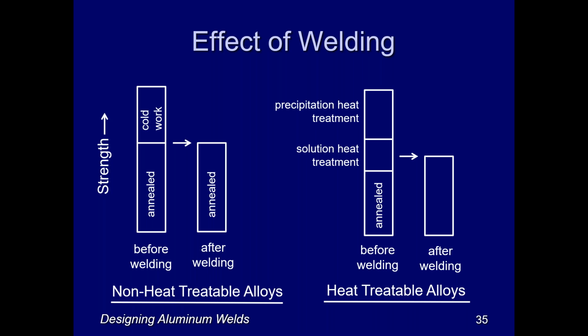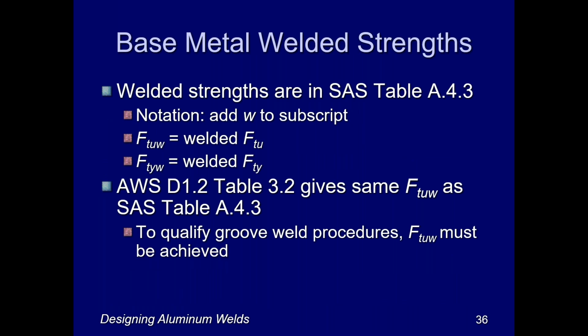And what we see there is that if we've done a precipitation heat treatment in addition to a solution heat treatment, so we have a T5 or a T6 temper, for example, when we weld it, we're going to reduce the strength to something less than the T4 strength, but something a little bit more than the annealed strength. So what is that strength? How do we know what that number is? Well, fortunately for us, the welded strengths of the base metals are listed in the Specification for Aluminum Structures in Table A.4.3. And the notation there is to add a W to the subscript. So when you see F sub TUW, that means the tensile ultimate strength in the welded condition. And the TYW would be the yield strength in the welded condition.